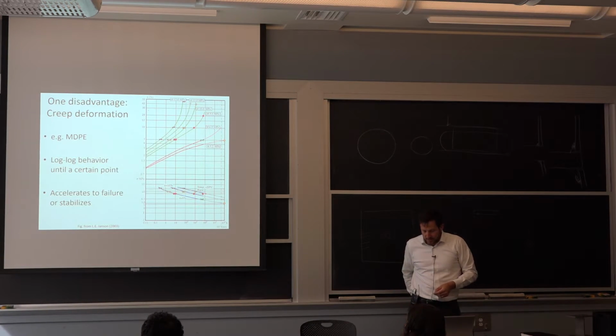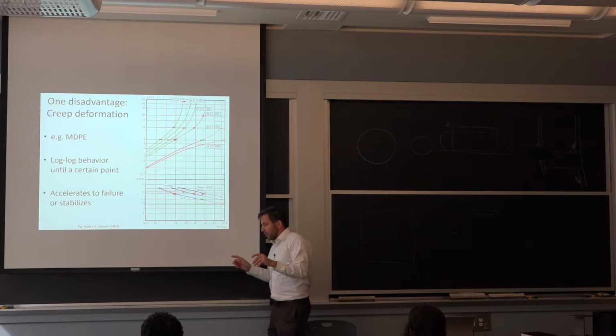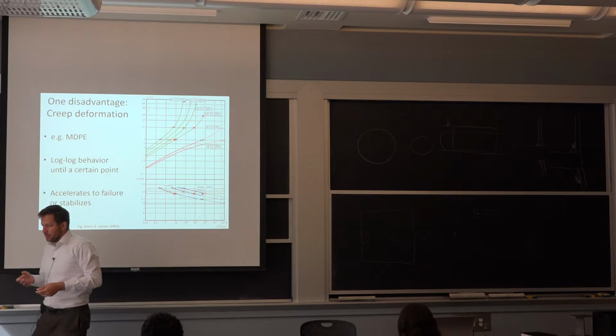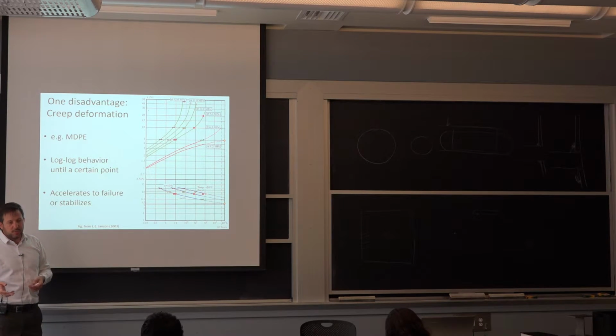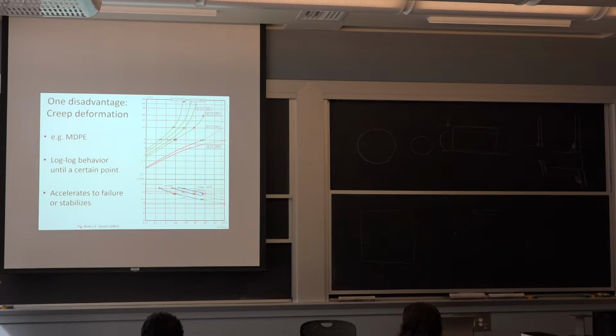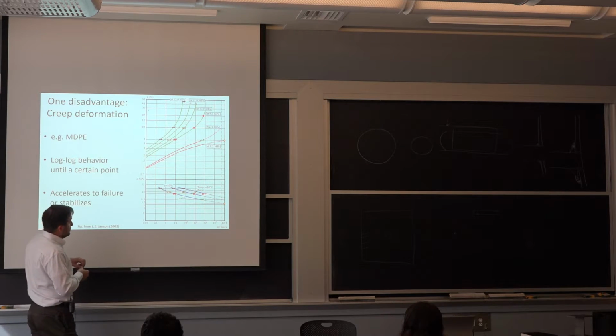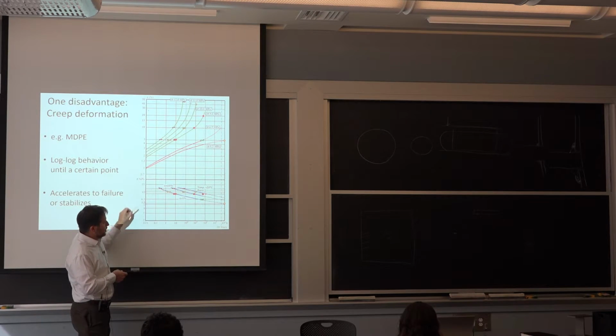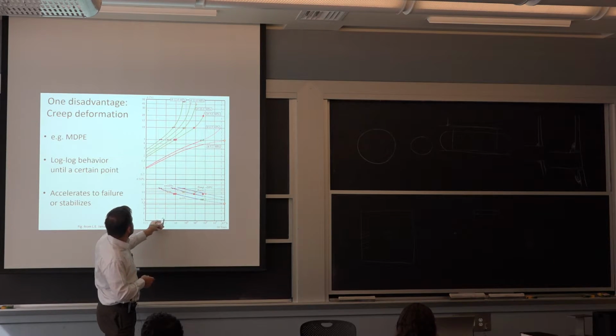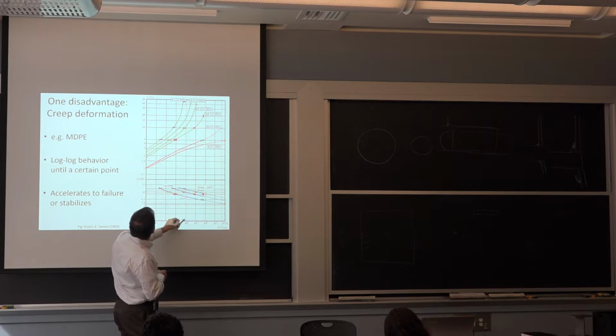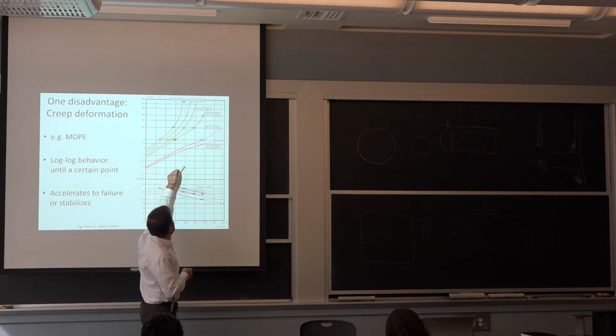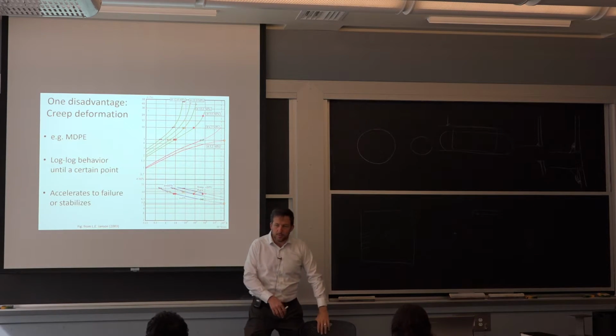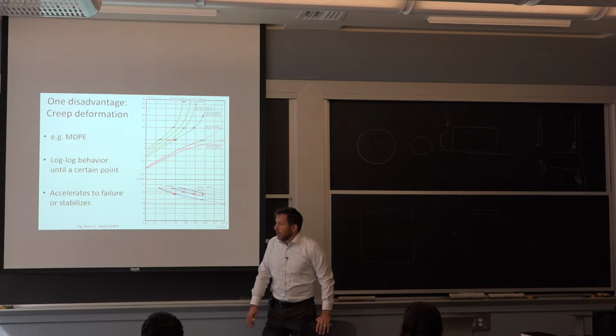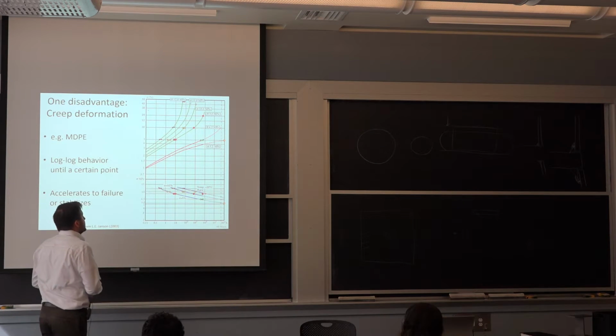So again, the biggest concern really with using a plastic is that if it's for a sustained load, a load that you put on and it stays there, it will deform over time. And the deformation, we're looking at polyethylene here, happens on a logarithmic scale. So you get a little bit at the beginning. So say here, this is after a day. So after a day at a given load here, what do we have? 5 megapascal, we got 3% strain. So that may be kind of applicable to something like this here. And that's fine. I can do that, get a viscoelastic strain.